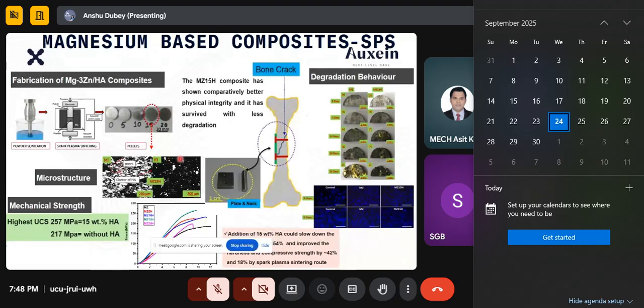So the first target was to optimize the composition, that is, how much percentage of hydroxyapatite we can use in the magnesium. So we took the spark plasma sintering machine and we made these composites with an increasing percentage of hydroxyapatite. And we found that 15% gives very nice results. We took the microstructure, and in this dark field imaging, these white portions are magnesium, and these dark portions are hydroxyapatite, which show a little agglomeration. Because the hydroxyapatite we used is nanoparticles, they have the tendency of agglomerating because of the high surface area.